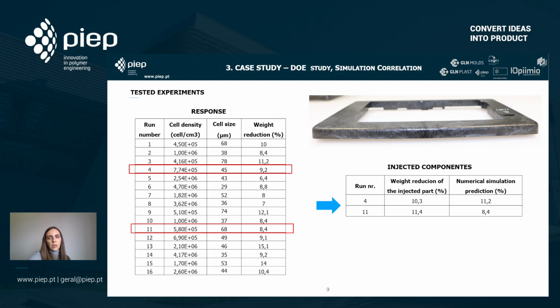However, for run number 11, we could see that we have a bit of change here. We have almost 3% of variation, which is not very high for this part because the part weighs 100 grams, and so 3% is not a lot. However, we wanted to evaluate why this variation occurred in this case specifically, and we did the correlation analysis in this part.